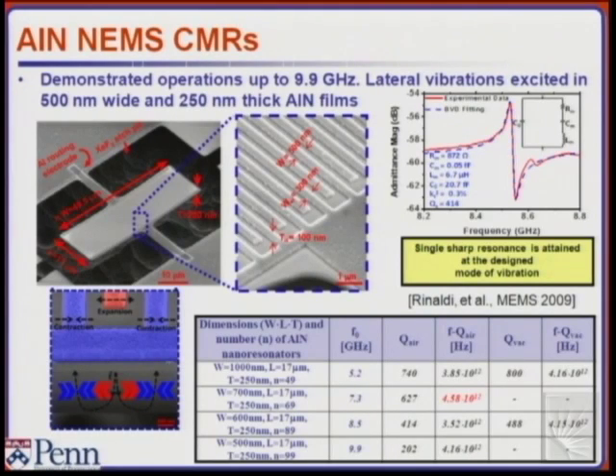And what is interesting is that the model stays the same. You get the same type of devices. Here, the RM wasn't properly designed. We're getting actually 800 ohm in this one, the one that was reported at the conference on NEMS 09. We really can make now 100 ohm or 50 ohm, even at this frequency, even at 8.5 gigahertz. And what's very interesting is that the Q is actually relatively high. I mean, we're getting Qs in the 500 to 600 or 700 even at these frequencies.